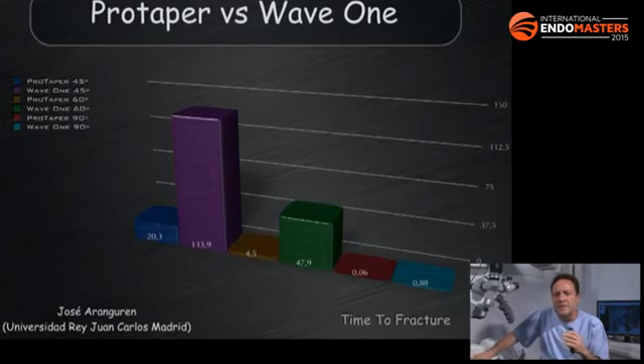Second thing, Pro-Taper and Wave.One don't have the same cross-section, and that will also play a role. And also the movement will play a role. So the combination of the alloy, the cross-section, and the movement makes it that you go almost 20 seconds with the Pro-Taper, and you go 133 seconds with the Wave.One. Now what you can see on the right-hand side of the graph with the 90-degree curve is that with Pro-Taper it's 0.06 and with Wave.One it's 0.88. And you see that both times are smaller than the second.